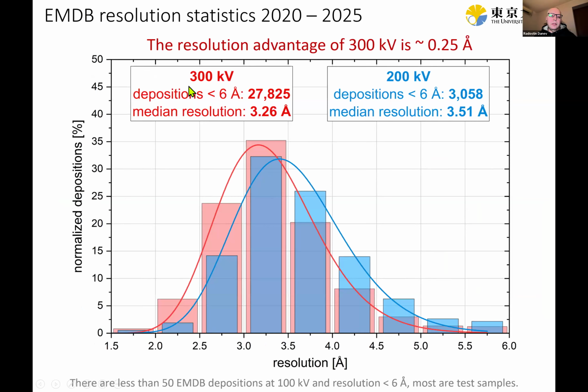Here you see statistics on the deposited structures, deposited maps in the electron microscopy data bank in the last 6 years. So we have the two histograms, and they have been normalized because the total number of structures, as you can see here in the boxes, is roughly 9:1. So the histograms are normalized, and then we also fit those with log normal distributions. They fit very nicely, and surprisingly, the difference in resolution is just 0.25 angstrom. So it's a quarter of an angstrom difference, but as you saw, the number of structures difference is so huge.